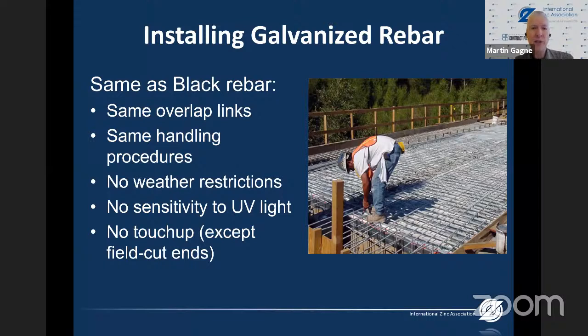Now, for designing structures to work with galvanized rebar, there's no change from working with black rebar. The same overlap lengths, same handling procedures. Some corrosion protection coatings such as fusion bonded epoxy are sensitive to ultraviolet light, so they cannot be stored outside. They have to be handled very delicately because if we scratch the paint, we expose the steel. We don't have any of these restrictions with galvanized rebar. The coating is very tenacious and robust. And we should not have any issues for repairing or touching up the rebar, except if we have to cut it in the field. We should put some zinc-rich paint or some solder on those ends to protect them.